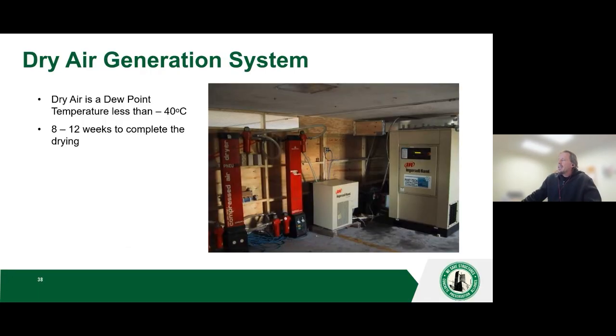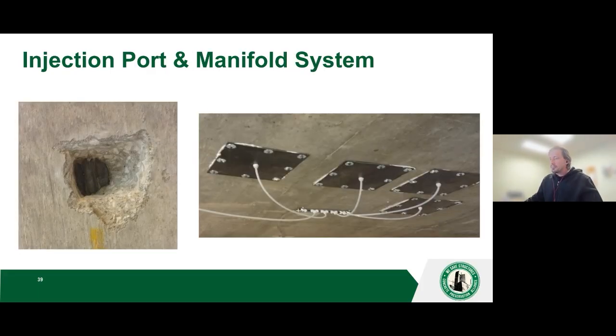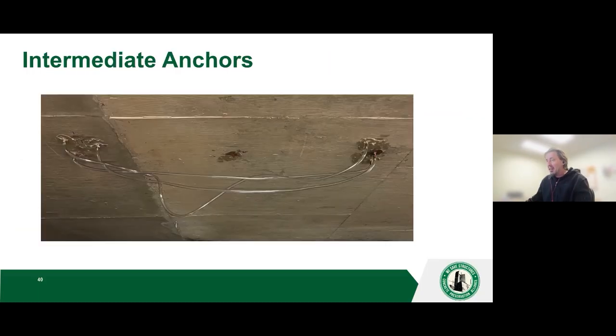What we do then is we use desiccant dryers and pump air into those tendons for 8 to 12 weeks to dry everything out. Once that's complete, here's the manifold setup. Like I said, we'll do numerous tendons at a time. On the left, these are banded tendons. So we've got 3 tendons. We can do those underneath one plate. Try to expedite this the best that you can, right?